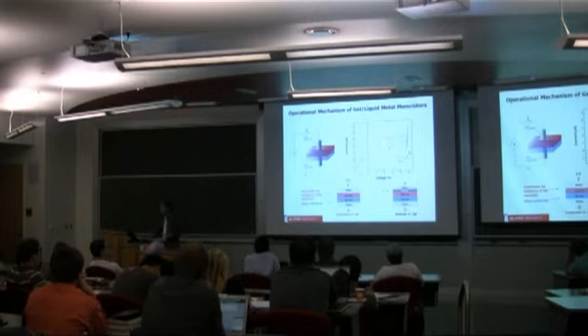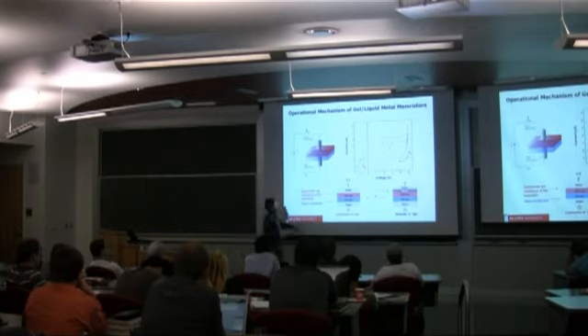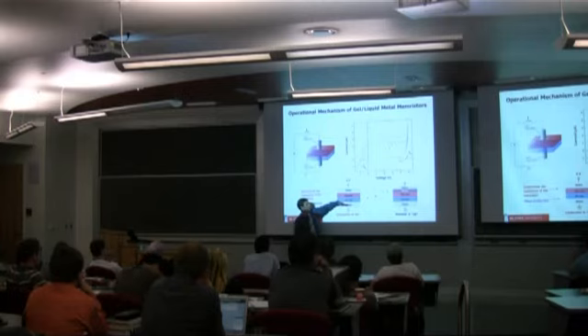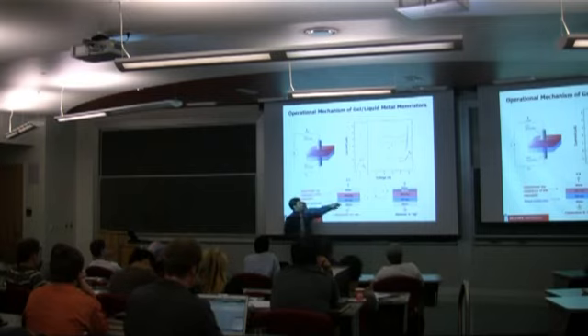When you go in the opposite direction, you reset the device and remove the oxide layer. Now the importance of the asymmetry here is, regardless of these two states, the base prevents the oxide from growing here. Otherwise you would switch back and forth between a state where the oxide's here and a state where the oxide's here. But by making it asymmetric, we keep this interface always conductive, and we switch this one between conductive